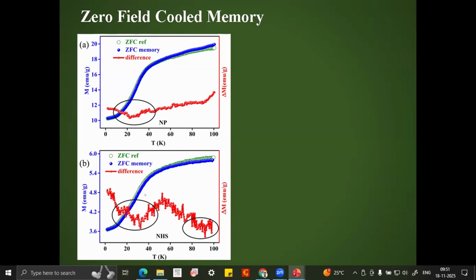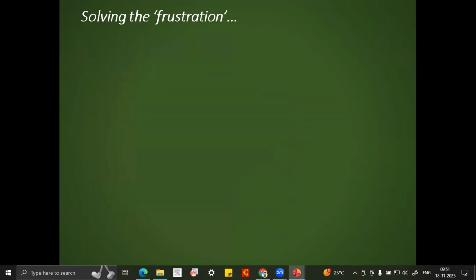On the other hand, for the hollow sphere, we are actually having a strong memory dip at 20 Kelvin and around 80 Kelvin. So this tells us conclusively that there is a superparamagnetic dominance in the nanoparticle. On the other hand, for the nano hollow sphere, the behavior is more like a spin cluster glass. Now, why is this cluster glass behavior happening?